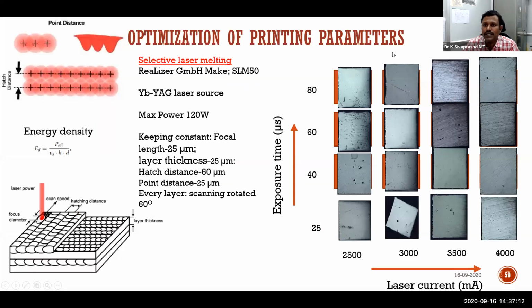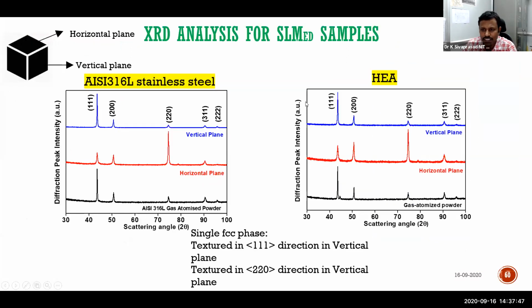Okay, then optimization of printing parameters was done, and when we have taken this material from a laser lower current to higher current and exposure time lower to higher, we could get decent optimization. There is a method to optimize SLM, and we have done it using that, and we have used even methods like Taguchi and even ANFIS models for this purpose, which I am not projecting here. So we have identified SLM conditions where you will get very few defects associated with it.